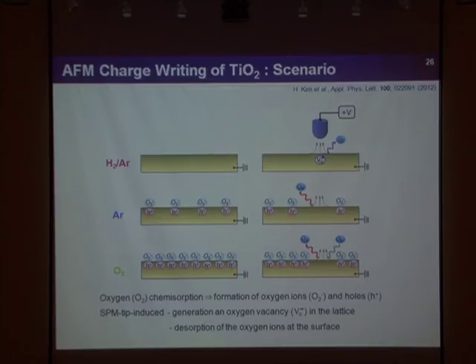Before inserting the sample in the AFM cell, I heat the sample for a while to remove water, so I can only say that the major absorbed gas is oxygen. Just after putting the sample in argon ambient, we can still expect some remaining oxygen. But when the sample is in oxygen, maybe more oxygen can be absorbed. But if you put the sample in the hydrogen ambient, we can expect most oxygen will be removed.